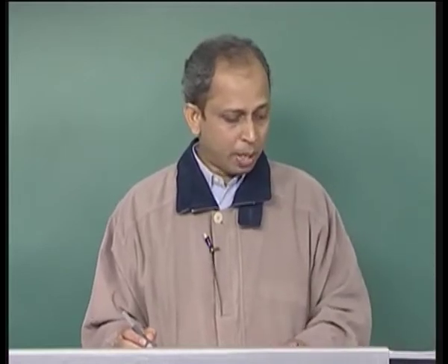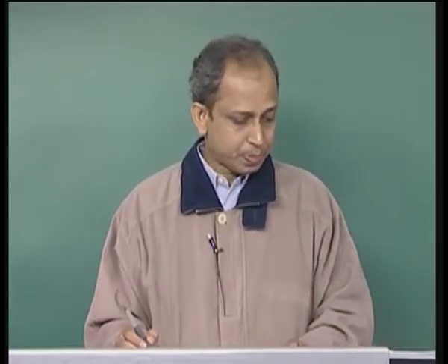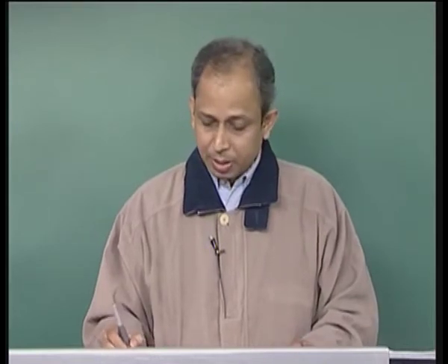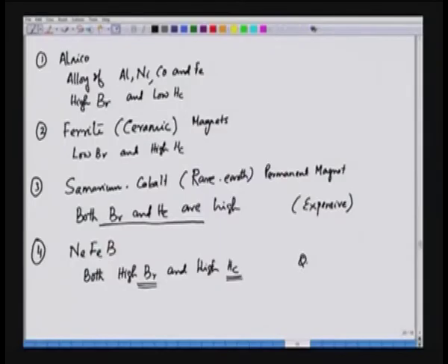The Curie temperature in this case is approximately 350 degree centigrade, and the Curie temperature of samarium cobalt is approximately equal to 700 degree Celsius.